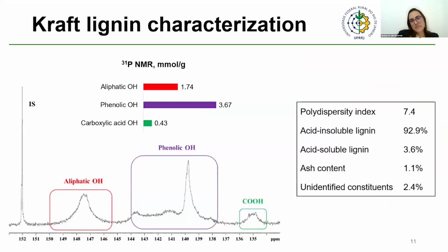So to understand the polyurethane properties, we did the lignin characterization. The lignin characterization indicated a high polydispersity index, suggesting a wide range of molecular sizes, along with high purity of this lignin. As we can see, acid-insoluble lignin was around 93%, while acid-soluble lignin was around 4%, giving us around 96% pure lignin.